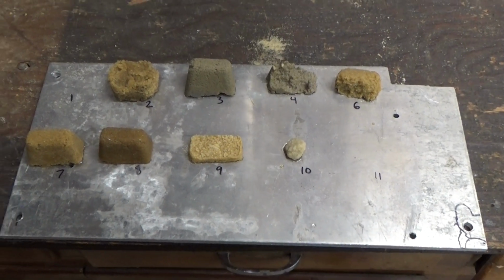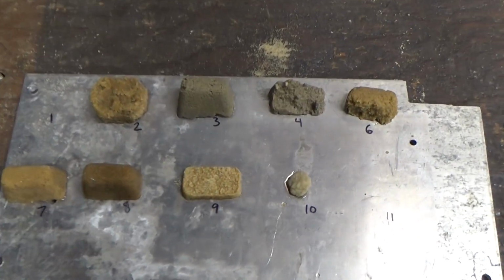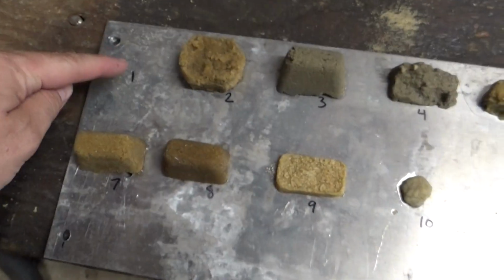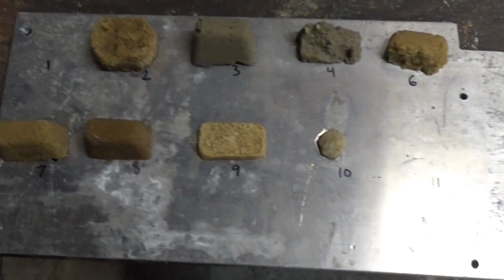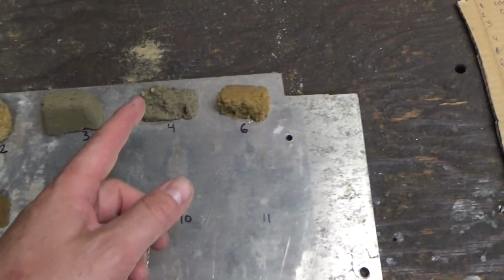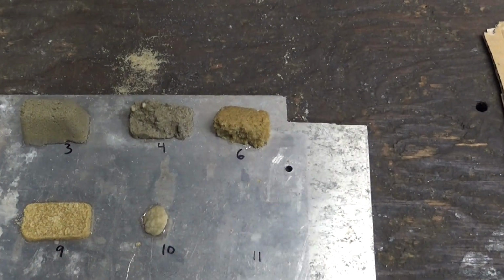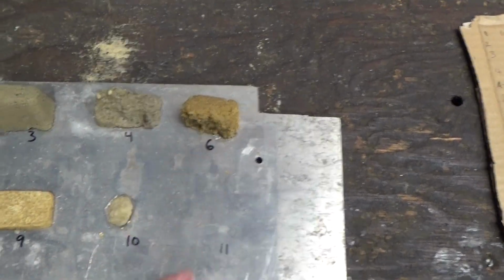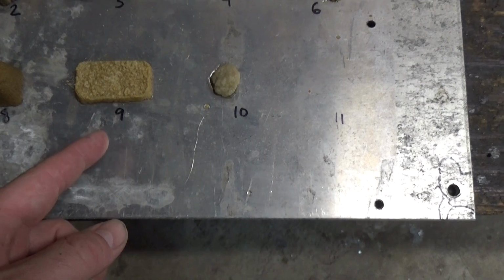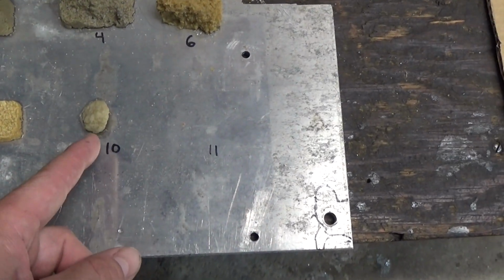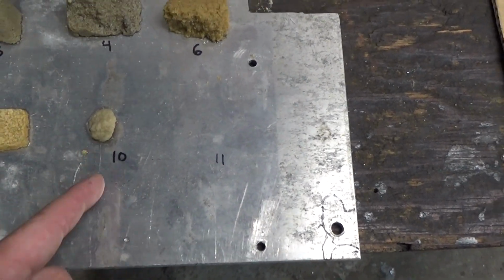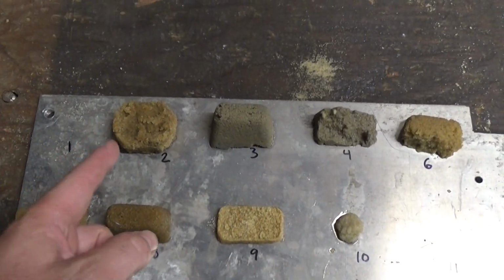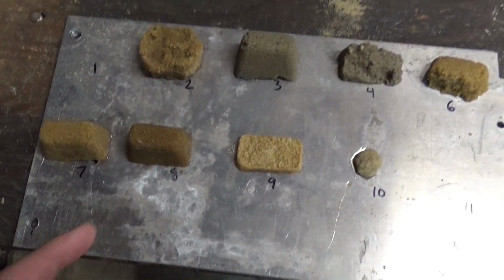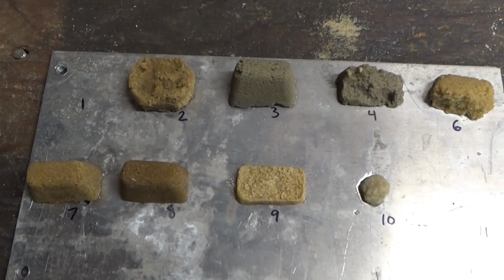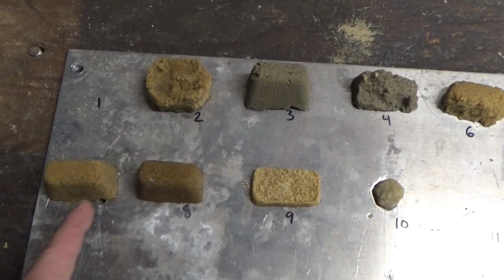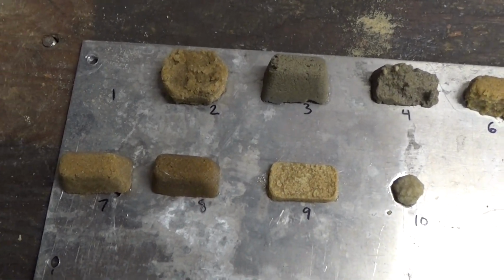I gave these samples a longer soaking, and this is the final result. So number 1 and number 11 we've had 100% loss of the material. Number 4 we've had about 60% loss of material. Number 6 we've lost about 40%. Number 9 we've lost about 80%. Our raw sandstone number 10 we've lost about 50%. And then as far as I can tell, 2, 3, 7, and 8 have lost very little, maybe 1% of the material. So those 4 samples seem to be the most water resistant at this point.